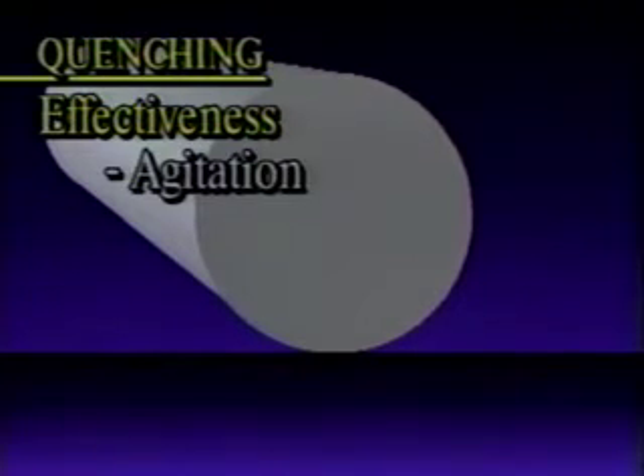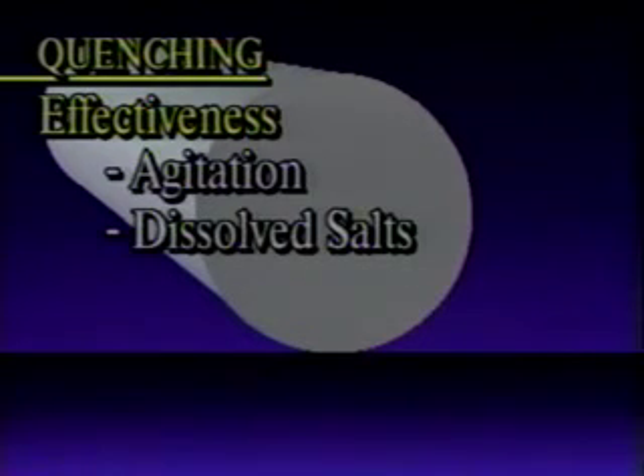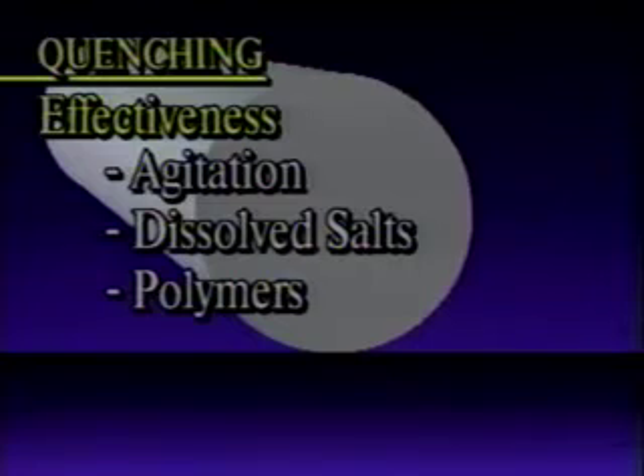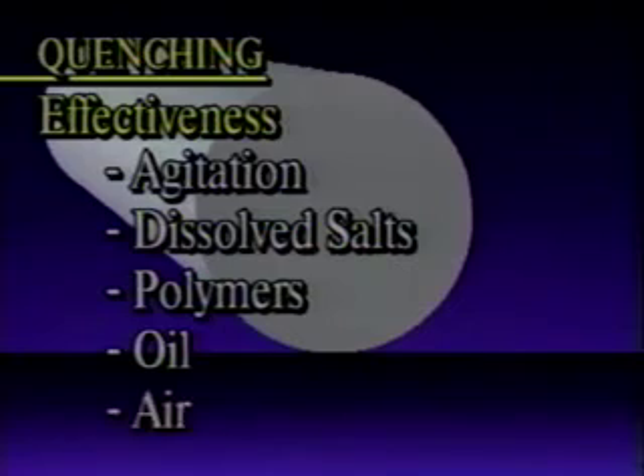The speed of a water quench can be increased by dissolving salts in the water. Sodium chloride or caustic soda in water solution greatly increases the cooling ability and therefore the speed of the quench. To reduce the cooling ability of a water quench, certain polymers can be dissolved in the water. Using oil for the quench provides an even slower cooling rate. And for still slower cooling, the parts can be cooled in air.